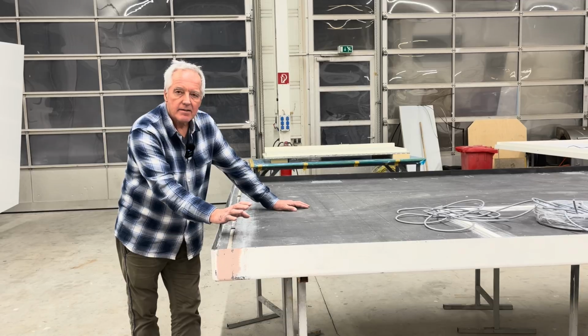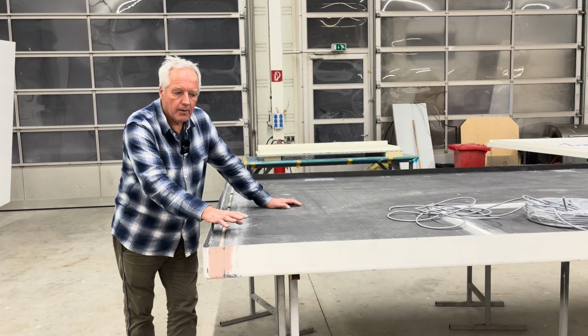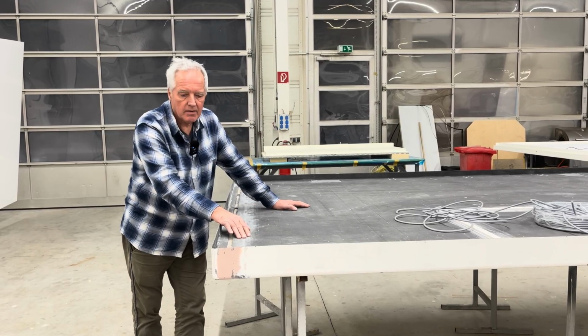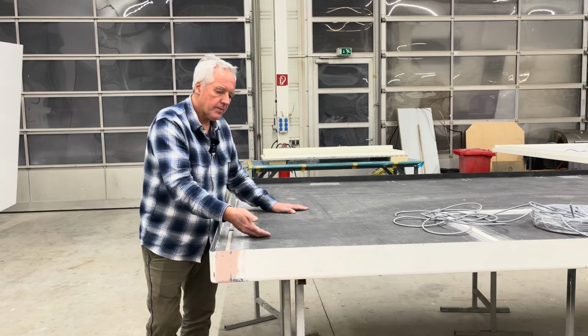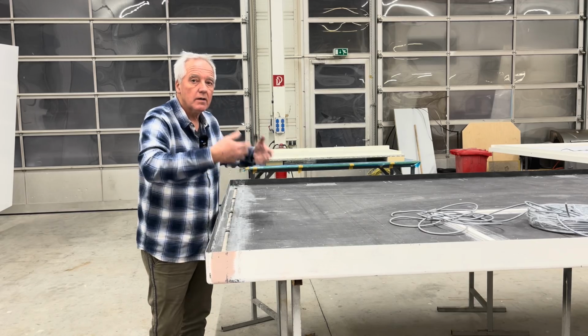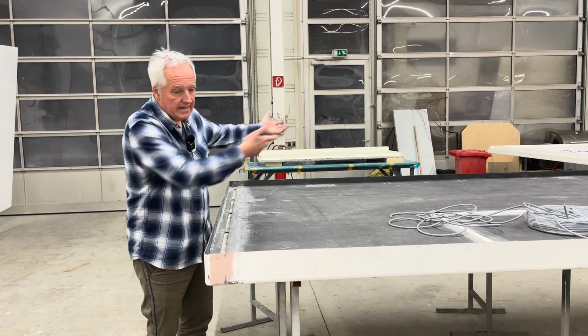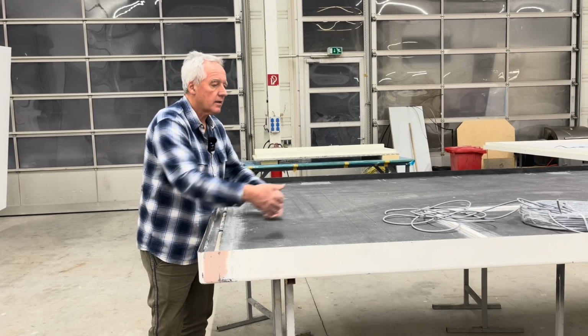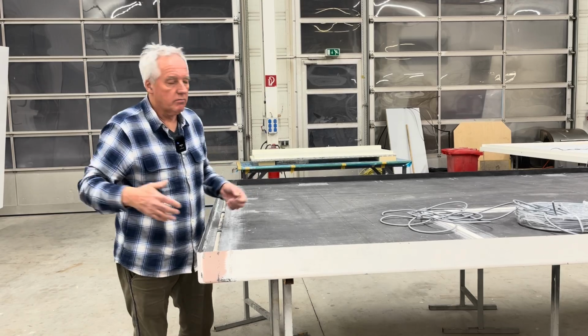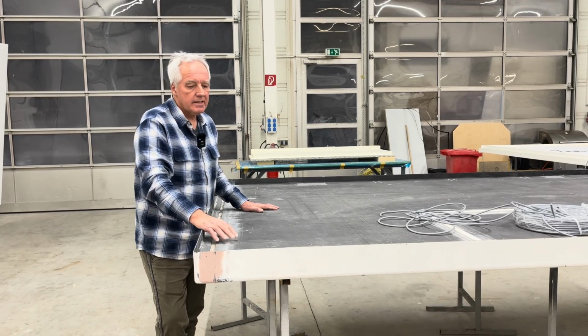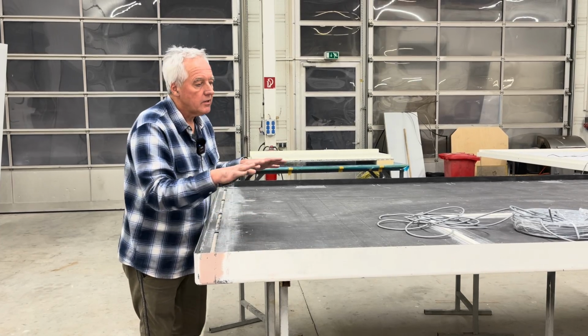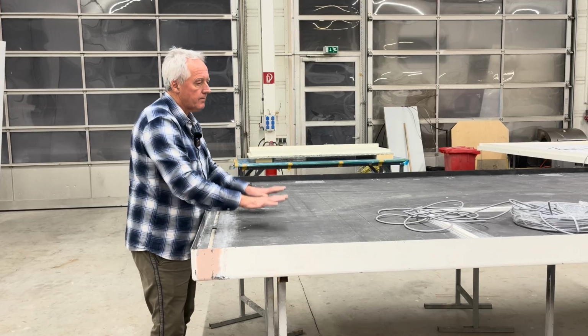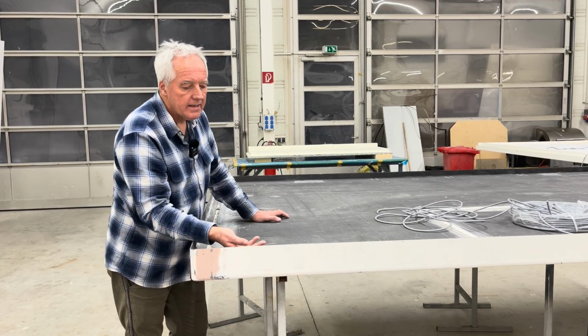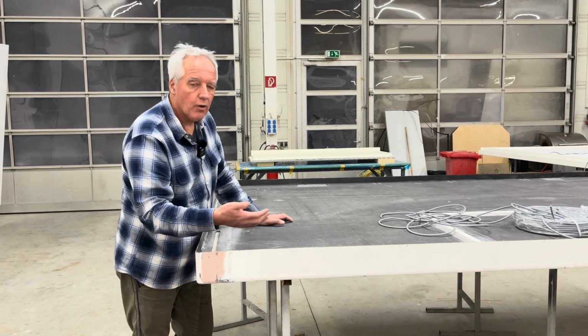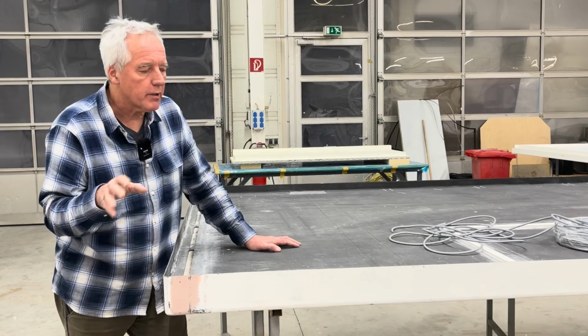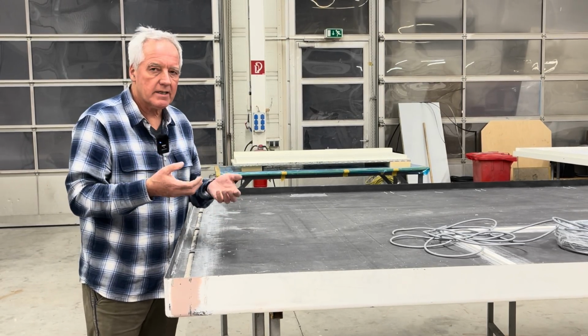And to maximize the weight to strength ratio, we are using so-called pre-pregs. A pre-preg is a carbon fiber mat, it comes as a roll, and you have to build a mold of this size, and then you roll in the carbon fiber pre-pregs like you would do with a fabric roll, and then you put the foam on top, and then you put more layers of pre-pregs on the inside, and then in the end you put a foil and put this foil under vacuum, so the whole thing is compressed.